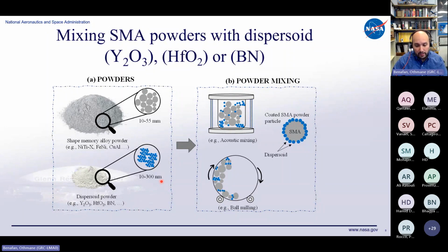This is not in the micro scale or the micron level, but it's in the nano level. Then we take this powder plus the dispersoid powder and we mix it. We mix it using acoustic mixing, or we could use some sort of ball milling also. And the idea is to coat the SMA. In this cartoon, you can see one SMA particle of powder sphere, and then you can coat it with these little dispersoid powders, yttria for instance.